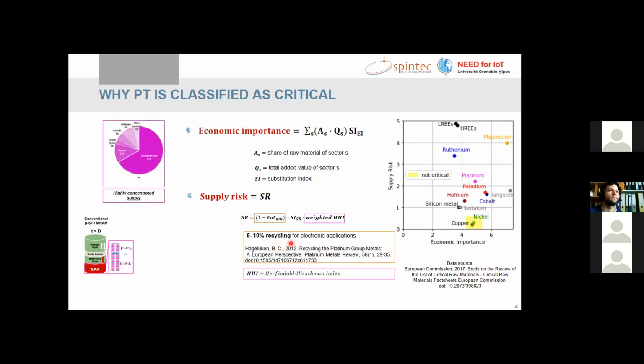Then there is the Herfindahl-Hirschman index that has also been referred to before, and gives you an idea of the concentration of the supplier of the material, and that for the case of platinum is mainly concentrated in South Africa and Russia. And finally, there is a substitution index that can decrease this supply risk, and this is exactly what I'm trying to do in my PhD. So, find possible alternatives for the use of platinum in this technology.